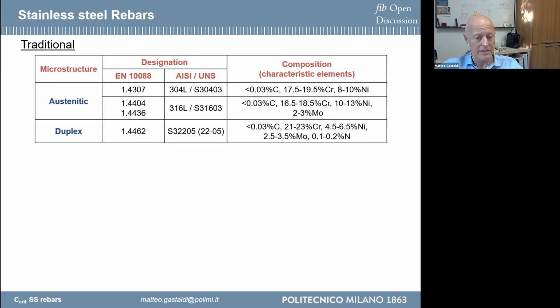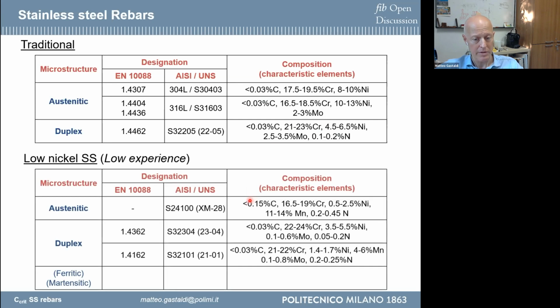For regions related to the coast, nowadays other kinds of steel are also proposed in the market: austenitic with low nickel, and duplex with no nickel. These kinds of stainless steel contain different alloy elements from the previous ones. In particular, you have manganese inside some of these steels, and this affects the corrosion behavior. I will try to go into detail on this. These different stainless steels have different corrosion behavior, and this is important to consider. When we want to design using stainless steel, it's important to consider that there is an effect of the difference in corrosion behavior related to the chemical composition of the steel.